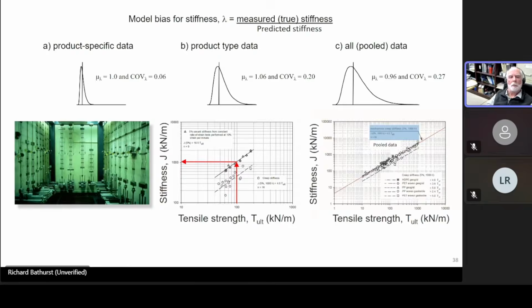If you simply take all of the stiffness versus tensile strength data that we were able to collect, and we were able to collect several hundreds of these type of data, and then you just use this overall correlation between ultimate strength and stiffness, then the accuracy in terms of spread, the coefficient of variation, is almost 30%.